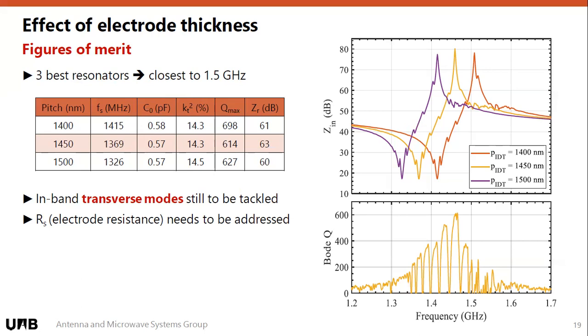We are actually way below the ideal achievable coupling that Kuznetsov predicted, because that was an initial study. They didn't take into account the thickness of the electrodes and the mechanical loading they provide. And there are many variables here. The fact that we have a layer transferred on the silicon oxide means you have interfaces with different crystallinity, etc. So you have things that are adding differences on top of your mode, but you have gone way above the expected limits in coupling that we had with other technologies.